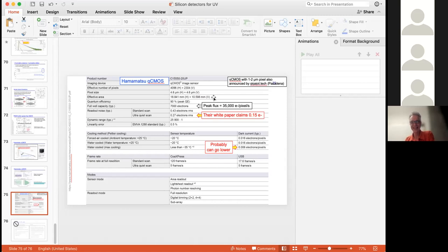Hi. Well, naturally my ears went up when you were talking about making really thin and thinner and thinnest detectors. Would you be interested in a situation where you got a smattering of different thicknesses? Some which were 0.5 micron, some 1 micron, some 1.5, just a wedge going across a bunch of different detectors, because that's probably what you're going to get first off. You don't mean as a test, you mean that it'd be difficult to control the thickness. Yeah, right off the bat it's going to be difficult to control, and that way you can at least figure out the benefits of different thicknesses.